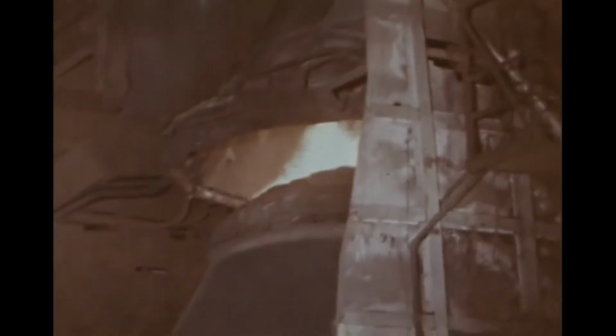Now comes the time to really fire her up. From high overhead, a water-cooled pipe descends slowly toward the open mouth of the vessel. Pure oxygen courses through the pipe, 20,000 cubic feet of it a minute, causing the molten mix to roar and churn, and raising its temperature to 3,500 degrees.